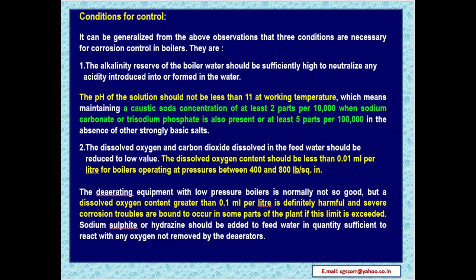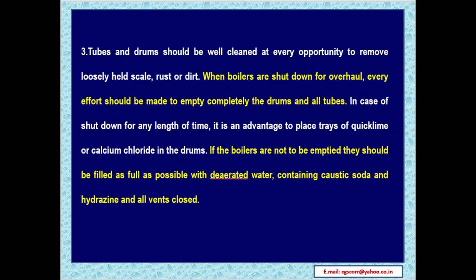Sodium sulphite or hydrazine should be added to feed water in quantity sufficient to react with any oxygen not removed by the deaerators. And tubes and drums should be well cleaned at every opportunity to remove loosely held scale, rust or dirt. When boilers are shut down for overhaul, every effort should be made to empty completely the drums and all tubes.